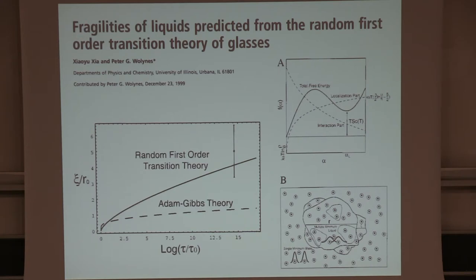Weirdly, that turns out to depend, since it's an entropy, logarithmically on how much things are confined. And we know that things are confined only about 1/10 of a particle spacing in their vibrations. There's a thing called the Lindemann criterion. If you try to vibrate bigger than that, the geometry of three-dimensional space makes it very hard for you to stay stable. Then you get an actual number for this surface tension. It's a very simple number. Also, it depends logarithmically on something that's thought to be almost the same for everything. So a logarithm of a number that doesn't change much is a number that doesn't change much at all.